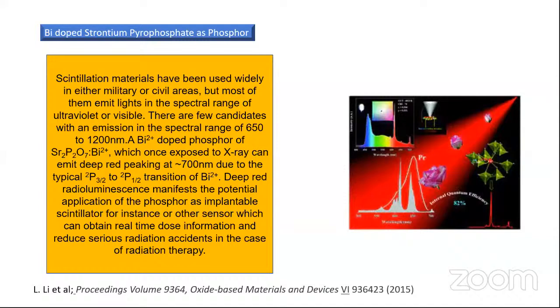Bismuth-doped strontium pyrophosphate, Sr2P2O7 doped by bismuth, once exposed to X-ray can emit deep red light peaking at 700 nanometers due to the typical 2P3/2 to 2P1/2 transition of bismuth. This deep red radioluminescence shows the potential application of the phosphor as an implantable scintillator, for instance, as a sensor material. So this is a very useful application of bismuth-doped strontium pyrophosphate. This reference was obtained, and the year of publication is 2015.